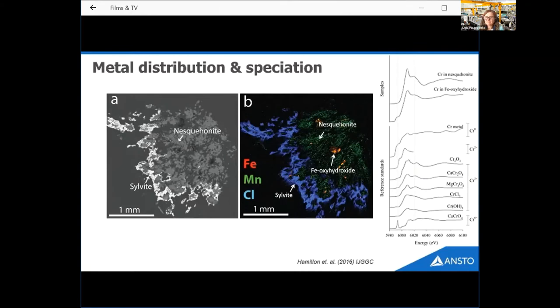And then we can extract another spectra from those hotspots of iron oxyhydroxide to see if there's any difference in those locations. What we found is that the spectra from both of those regions is really closely matched with the chromium 3 plus reference spectra. So that's good news. It means that chromium and the other metals that we looked at, they end up in the carbonate minerals, not in the leachate, where they could be potentially leached into waterways, for example. And we don't see chromium oxidizing into a hazardous form.